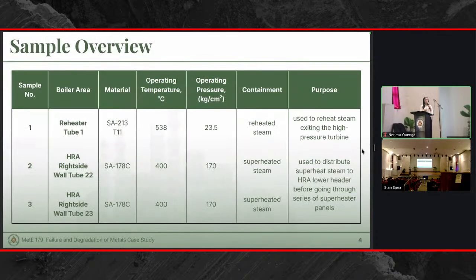Moving on to our materials overview, we have 3 failed samples, and we named them sample 1, 2, and 3 for our investigation. All these tubes are in one area, the hot reheat area, near a rotary soot blower. These tubes do not contain the same steam, but rather they are just located in one place. So sample 1, or reheater tube 1, is used to reheat steam exiting the high pressure turbine, and sample 2 and 3 are adjacent tubes, and they are both HRA right side wall tubes, used to distribute superheat steam to the HRA lower header before going through a series of superheater panels.